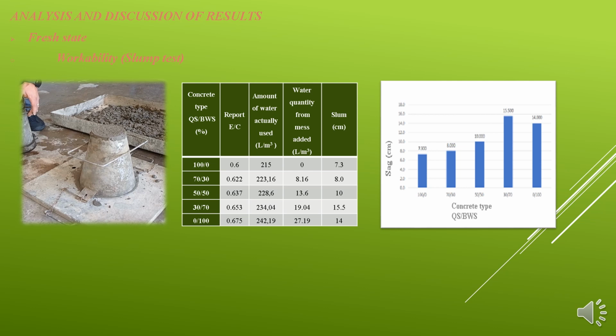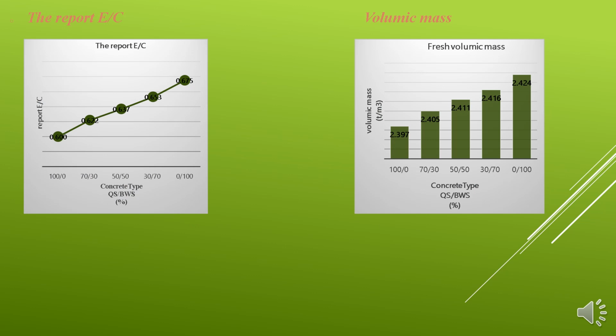From the curve which shows the different slump values, we note that the mixing water actually used to ensure this slump increases according to the rate of substitution by recycled aggregates on the one hand, and the type of aggregate on the other hand. Now, let me turn to the E/C ratio and volumic mass or density. From the curve of E/C, this ratio for the same concrete composition increases proportionally with the rate of recycled sand in the concrete mix.